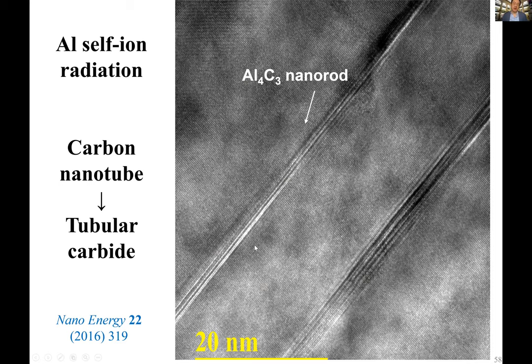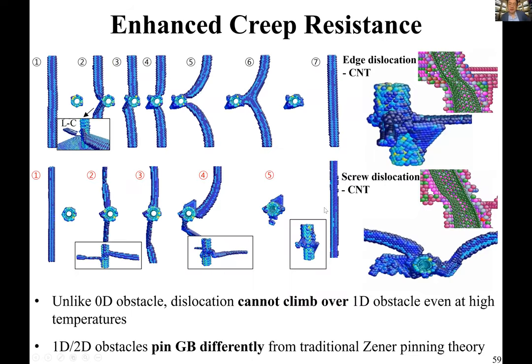But the question has always been how robust are the nanostructures themselves? Do they globularize? Do they try to reduce surface energy and turn into a sphere and no longer become a nanostructure? So we've shown that these carbon nanostructures can still maintain a large interfacial area, even up to hundreds of dpa.